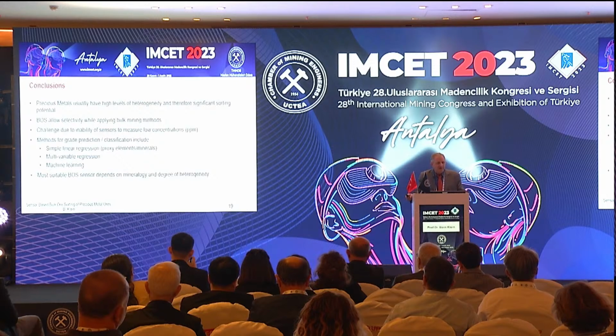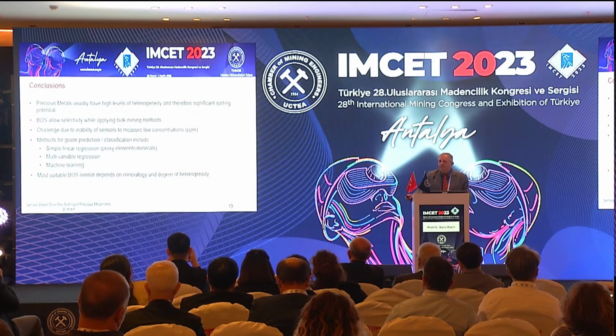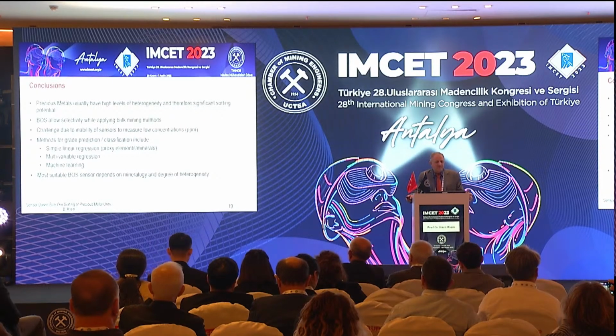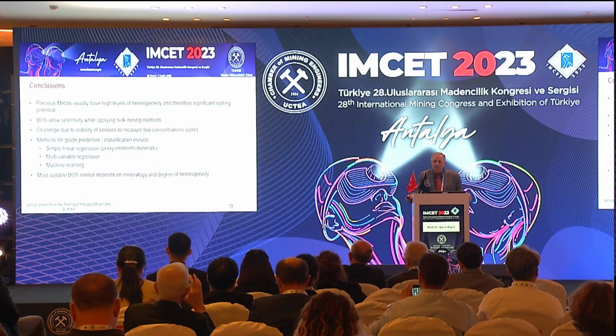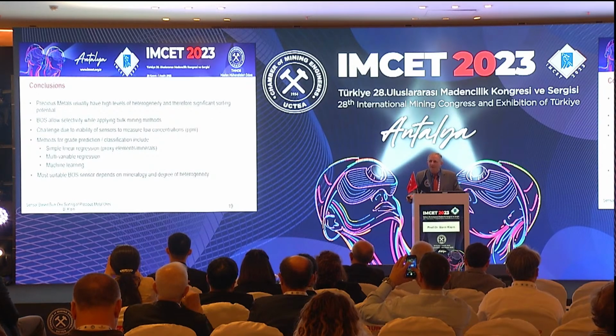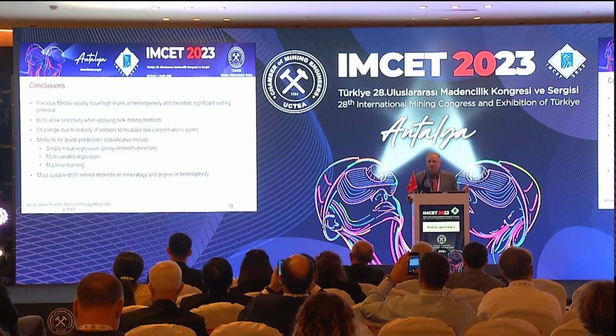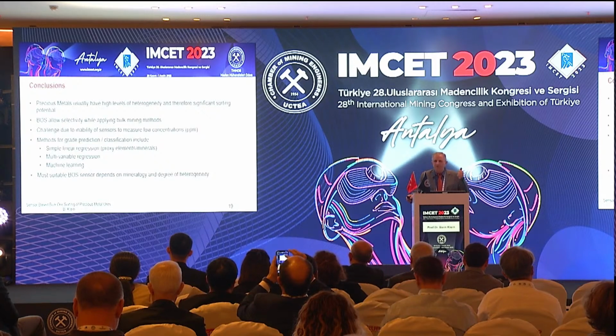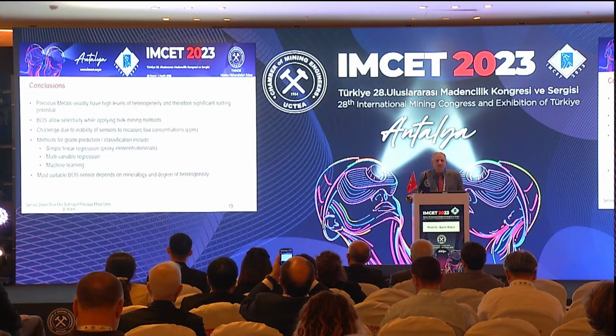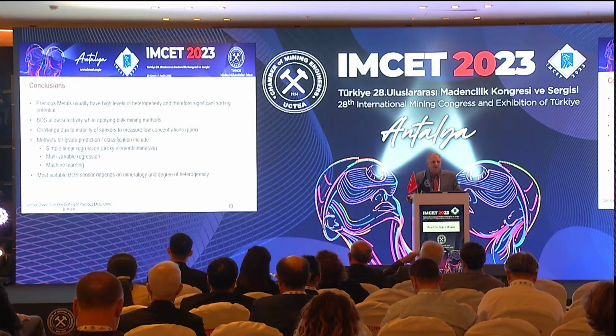So in conclusion, precious metals usually have high levels of heterogeneity and therefore have significant sorting potential. Bulk ore sorting allows selectivity while applying bulk mining methods, low-cost mining methods. The challenge is due to the ability of the sensors to measure low concentrations. There are methods, simple linear regression where you identify a proxy, multivariable regression, machine learning approaches that need to be tested and applied. And it's very ore specific. Depends on the mineralogy and the degree of heterogeneity within the deposit.